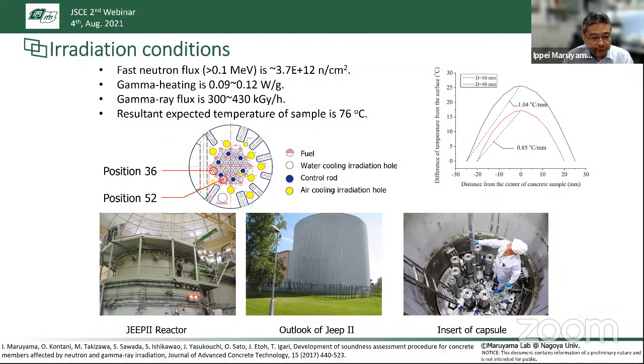For the neutron irradiation experiment, we use the Halden reactor owned by IFE Norway, which has been permanently shut down recently. This is a heavy water reactor, and it is suitable since the gamma ray flux is reduced during the irradiation. And as I mentioned, during the neutron irradiation, we see a large temperature increase inside the specimen. So, to get appropriate data, design of the specimen is really important. In our case, 4 centimeter diameter concrete specimens were used, based on the estimated temperature distribution inside the concrete specimen.